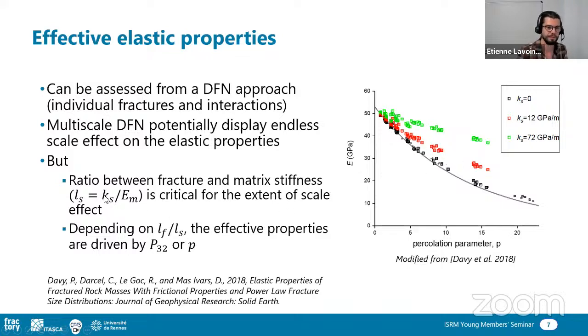And what we found out is that the ratio between the fracture and the matrix stiffness, so the ratio between the shear stiffness and the Young modulus, which is homogeneous to a length, is critical for the extent of the scale effect. And then you introduce this kind of characteristic length that I was talking about just before. So depending on the ratio between the size of the fractures and the size of this matrix-fracture stiffness length, the effective properties are driven either by P32 or percolation. But if you are interested, you can just have a look at this paper.